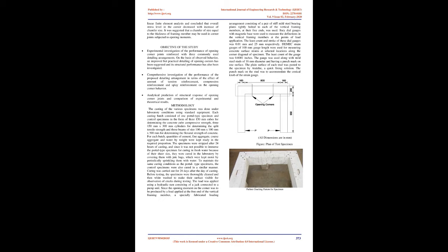For corners where the depth of any of the framing members was more than 500 mm, it was recommended to provide radial hoops along the diagonal of opening corners. Singh and Chaturvedi, 1997, reported that the efficiency of poorly detailed joints subjected to opening moments may be as low as 30%, however, when detailed properly, the efficiency of the joints is improved significantly.